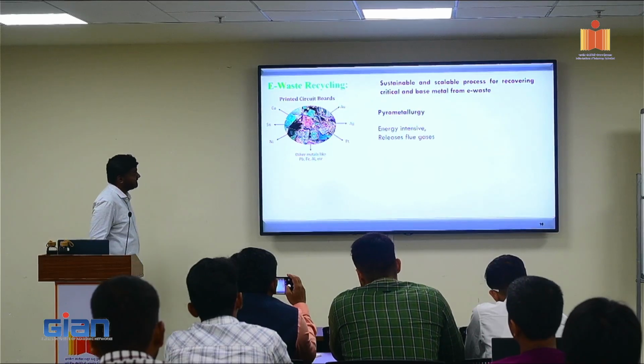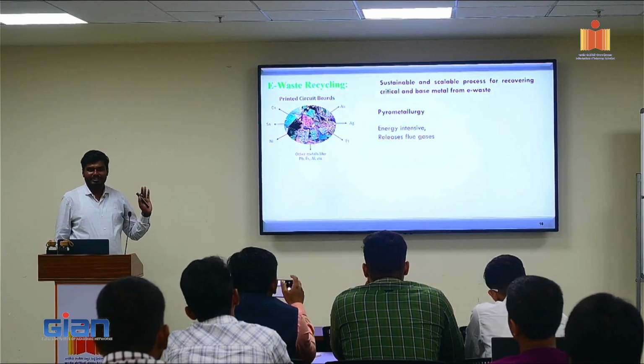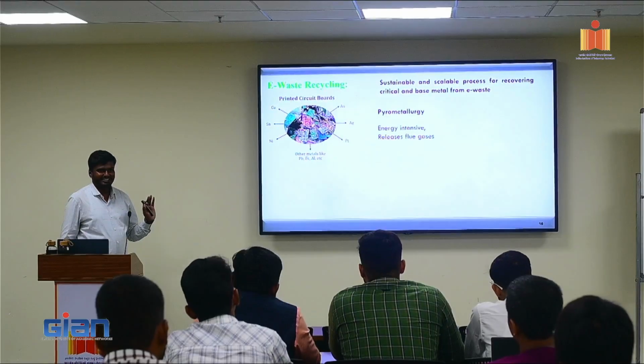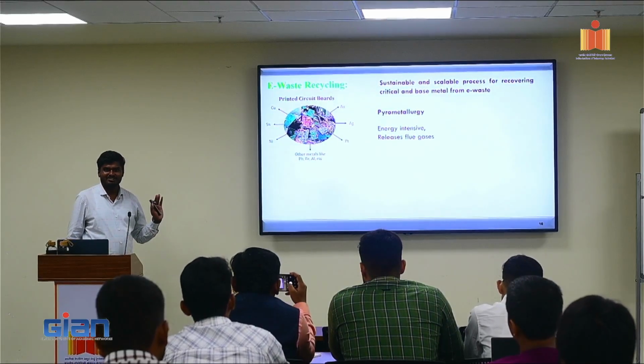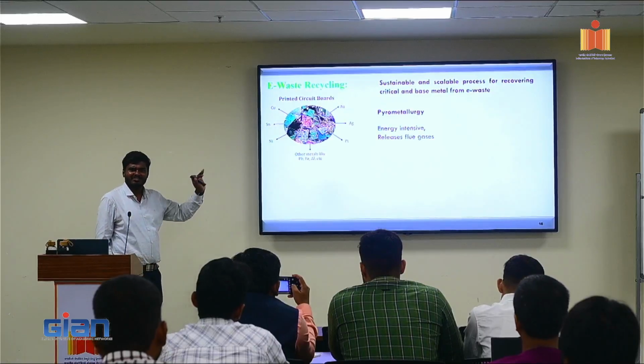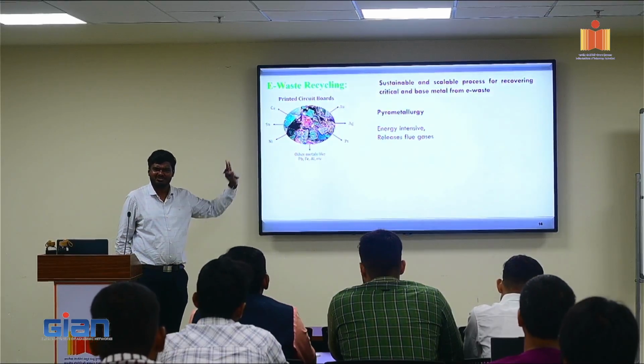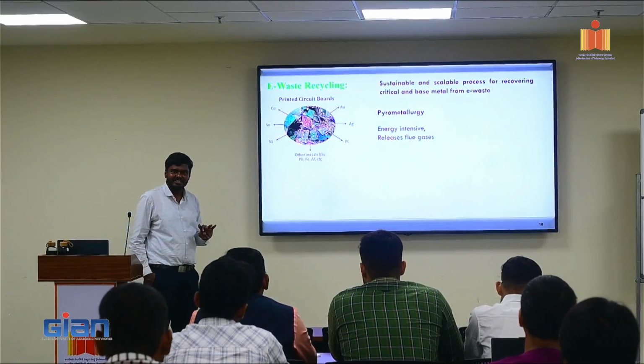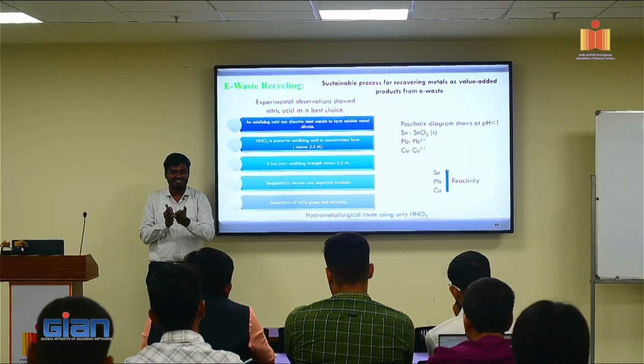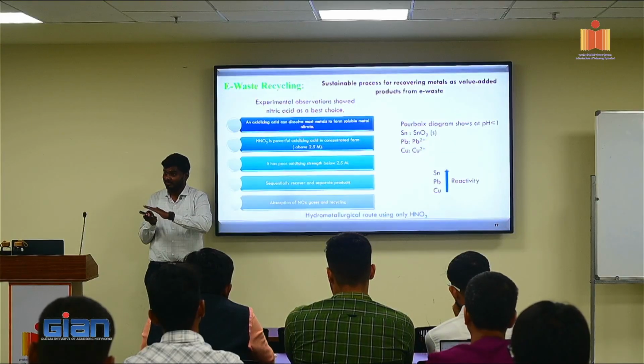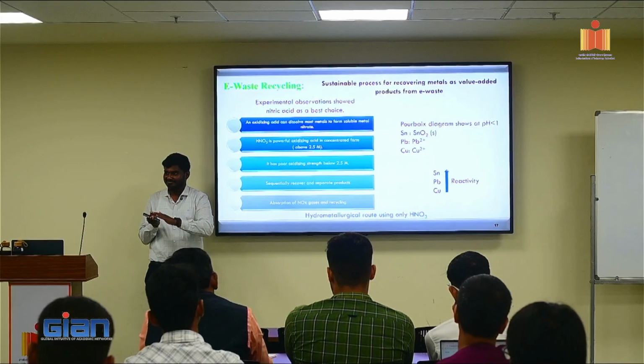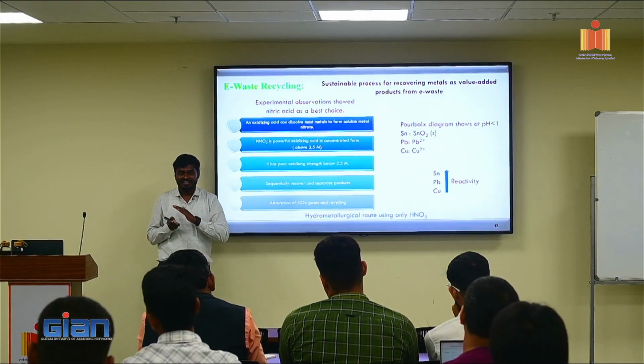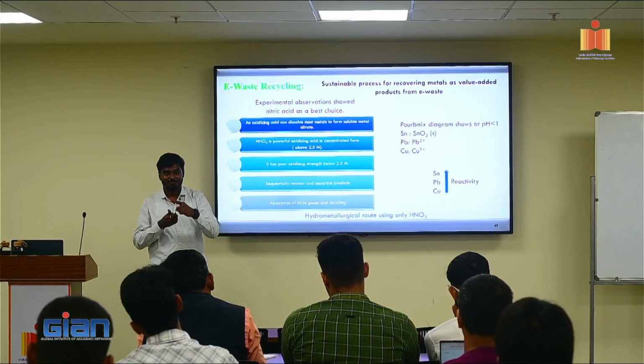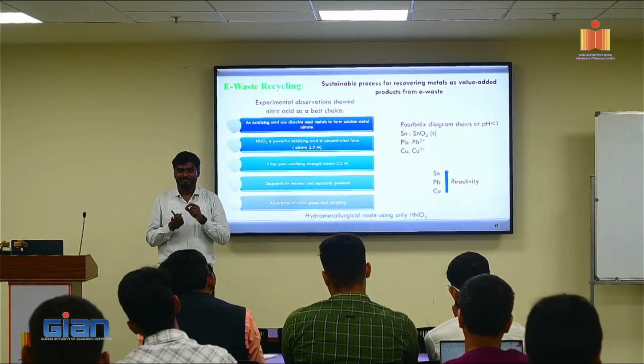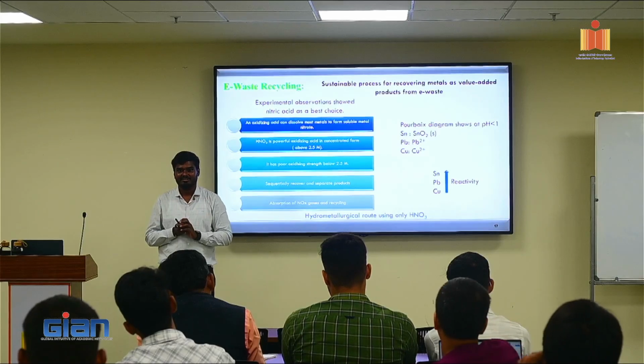Once this is there, you typically know the pyrometallurgy process. It is energy intensive and releases flue gases. So people who do hydrometallurgy always say that pyrometallurgy is energy intensive, we should not go. But in fact, if you see, industrial maturity is there. Lead and tin don't have any cover, whereas copper has an epoxy layer cover. You understand, right? So other metals have some resistance, some plastic coating or some epoxy layer, but lead and tin have direct contact with acid.